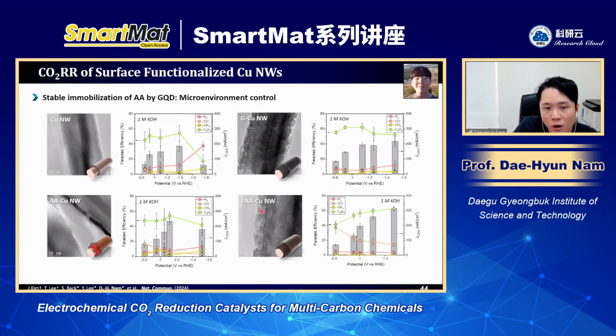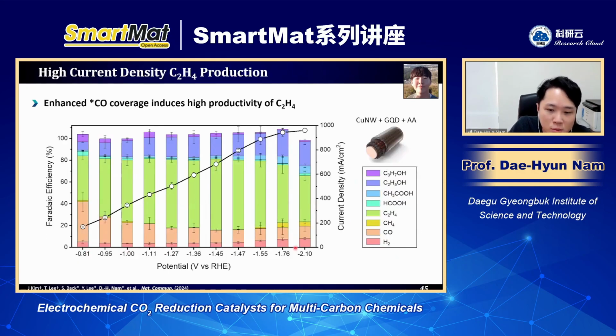our major result. Unlike this one, we can see the existence of CO at the low potential. It means that the CO production has been promoted in the low potential range. And then, although we increase the potential, this does not lead to a decrease of the ethylene; the ethylene FE maintains, and instead CO decreases. It means that the promoted CO2 to CO conversion has the merit of converting CO to ethylene. In this way, although we keep increasing the potential, we could maintain the FE for the ethylene to the high current density region. It's almost close to the 1 ampere per square centimeter scale.